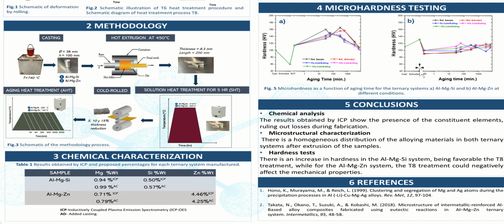On the other hand, the samples containing zinc do not present an increase in hardness when submitted to the rolling process and the thermal treatment of aging. The maximum value of hardness is obtained when the samples are submitted to the thermal treatment of solubilization and without a plastic deformation.